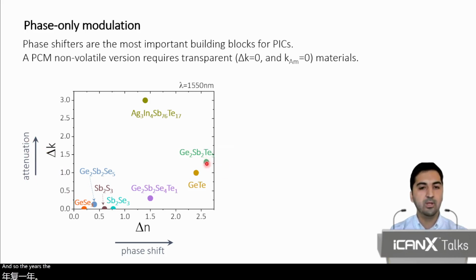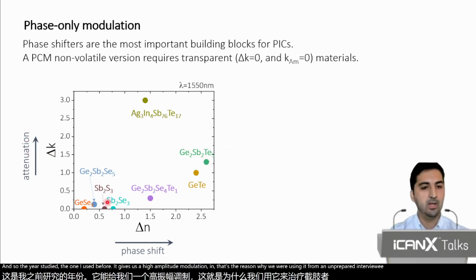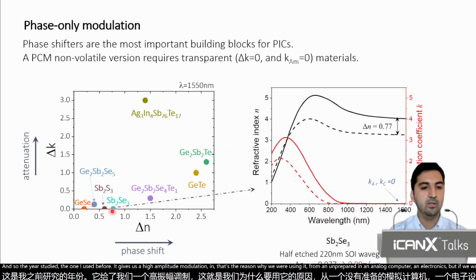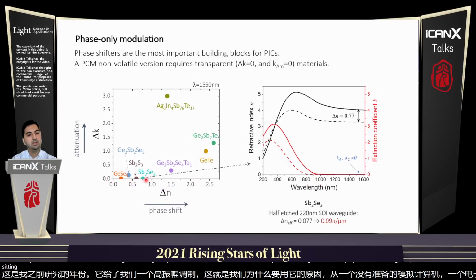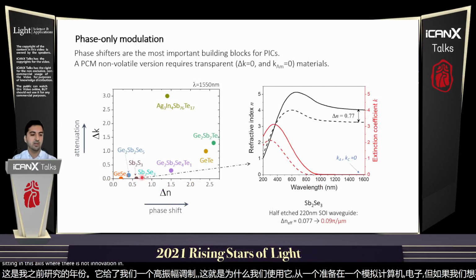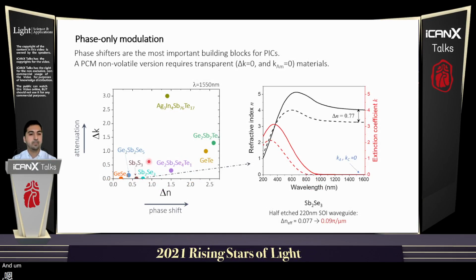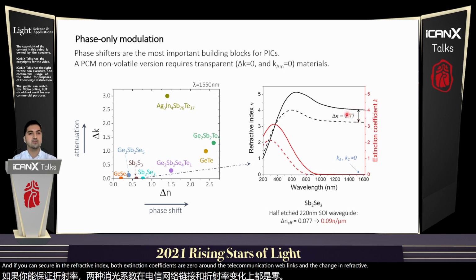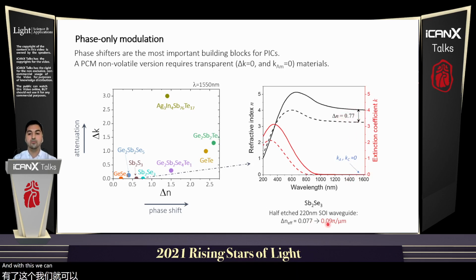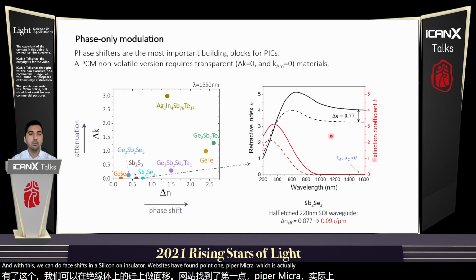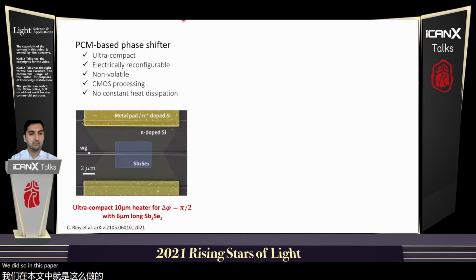So GST, the one I used before, gives us high amplitude modulation, and that's the reason why we were using it for amplitude and analog computing in photonics. But if we want to talk about phase-only, then we need to sit on this axis where there is no attenuation and find the largest phase modulation. To do so, we focused on this alloy called antimony selenide. As you can see here, the extinction coefficient is 0 around the telecommunication wavelengths, and the change in refractive index is still very large. With this, we can do phase shifts in silicon-on-insulator waveguides of about 0.1 pi per micron, which is really good. We did so in this paper that we put on arXiv recently.